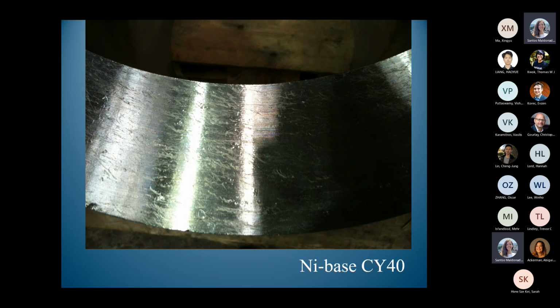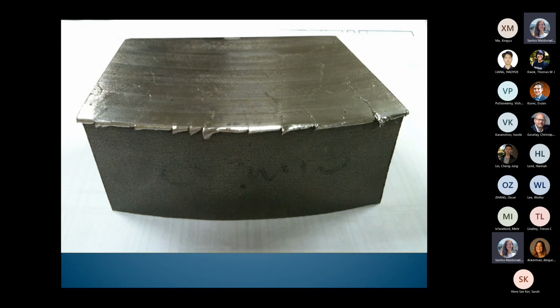And here is a very bad piece of metal turning in which we cast this nickel-based alloy. This is a beautifully ductile nickel-based material, but we cast it really quite badly in the early days before we knew how to cast the stuff. And what you can see is it's full of bifilms because the person turning had turned with a rather blunt cutting tool, and the cutting tool has torn open the bifilms on the surface. It's sort of ripped them open to make a really bad surface. And you can see they're everywhere. This is another shot from, again, I think it's the same nickel-based alloy.